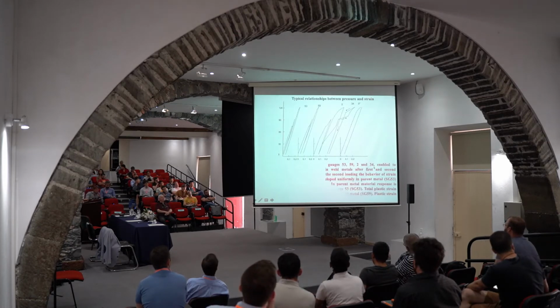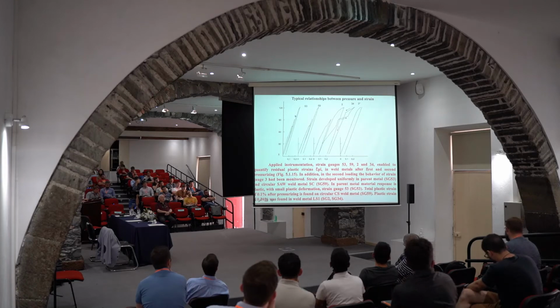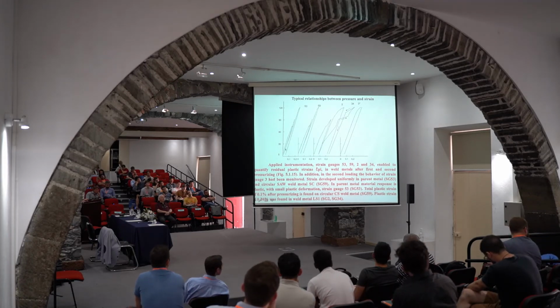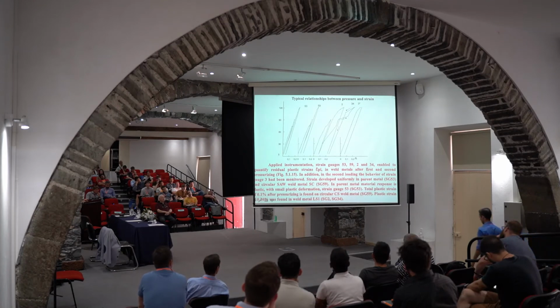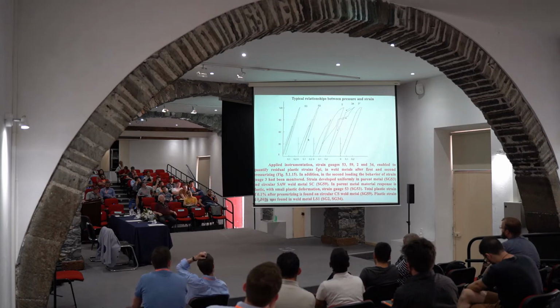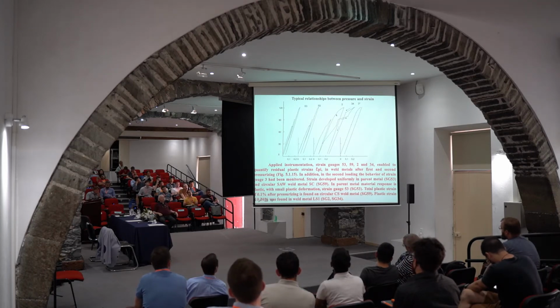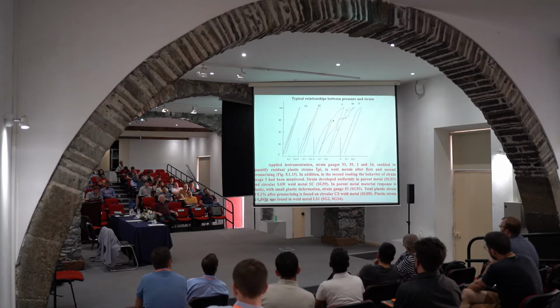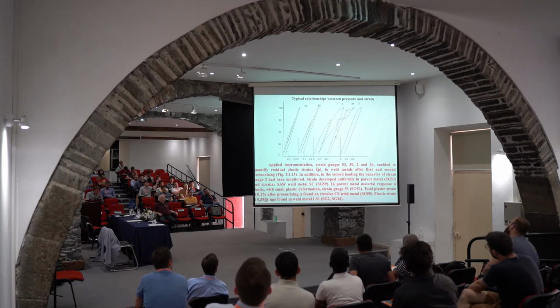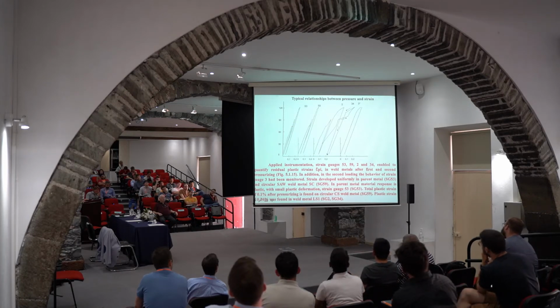And you can see it here. If you look at the strain gauge 53, you can see that this is pressure, this is strain. So strain follows the pressure, linear elastic, first stage, second stage, third stage, unloading, everything fine, as expected. Linear elastic behavior, also completely benign, almost for number 3, but with strain gauge number 2, which is one on the welded joint, you can see some non-linearity, and you can see that after unloading there is some plastic strain left.